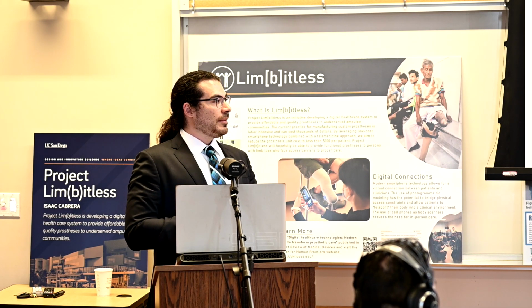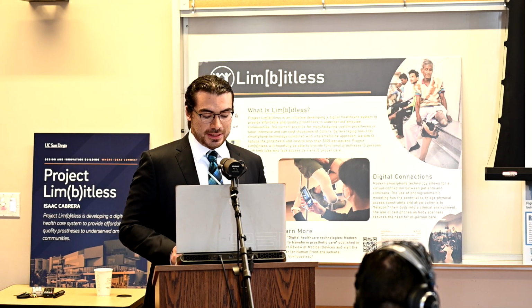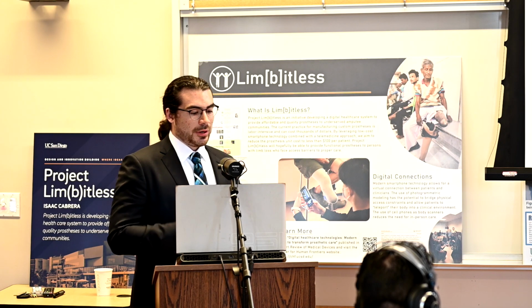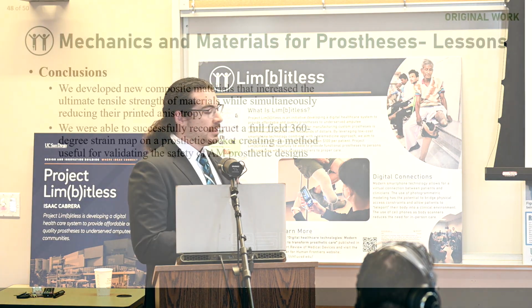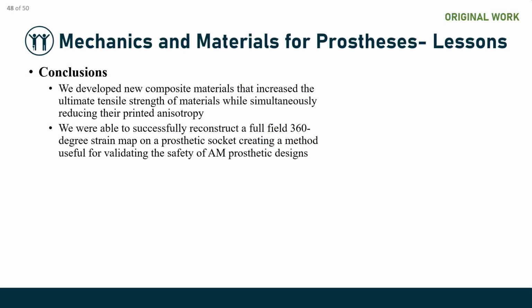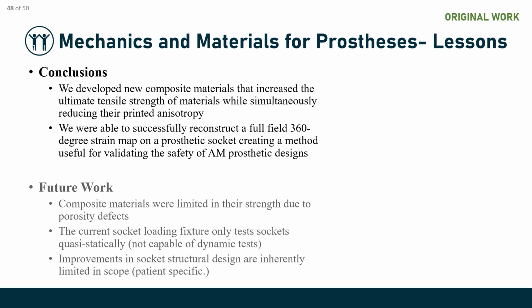So coming to the end, what are some of the lessons we learned? We were able to develop new composite materials that increased the ultimate tensile strength and also reduced the printed anisotropy. That was specifically with those urethanes and the carbon fiber filaments. In addition to that, we were able to build a full-field 360-degree system for mapping the strain on a prosthesis and to validate the safety of the prosthetic designs.